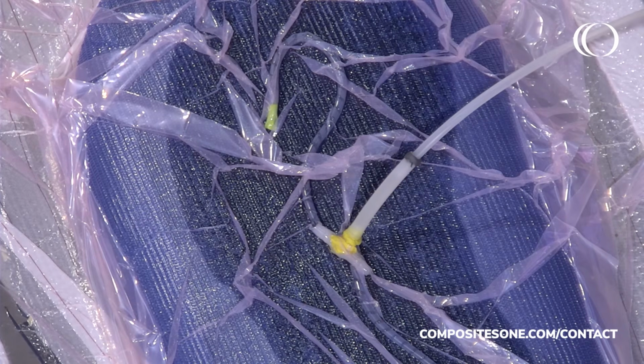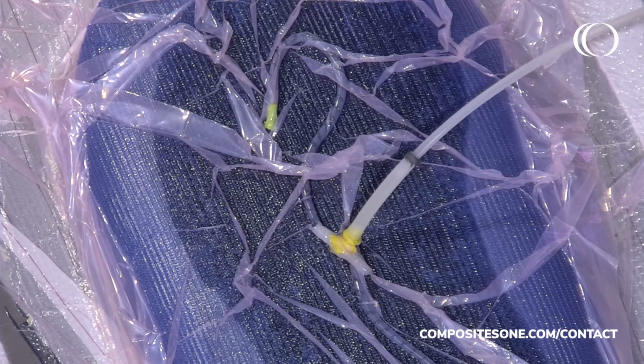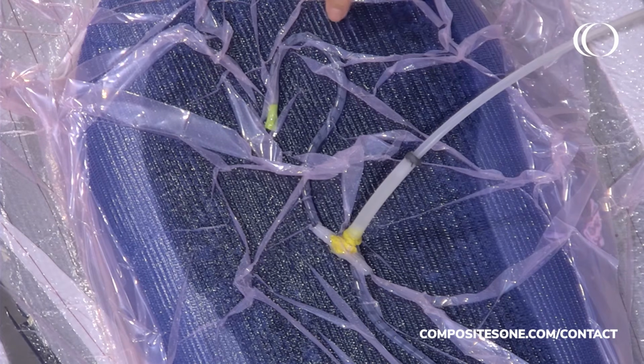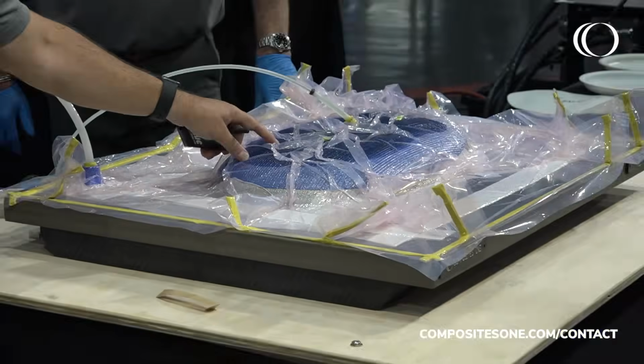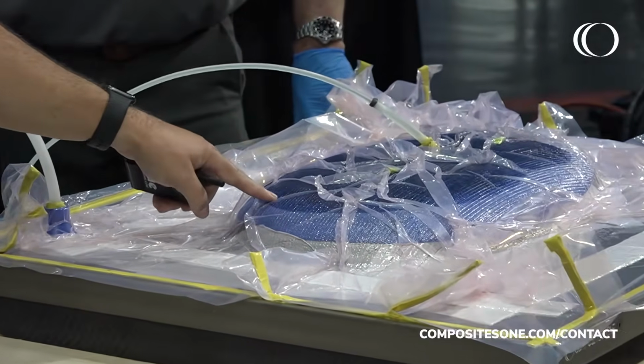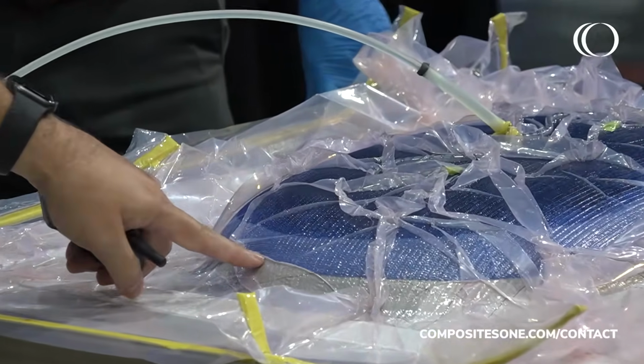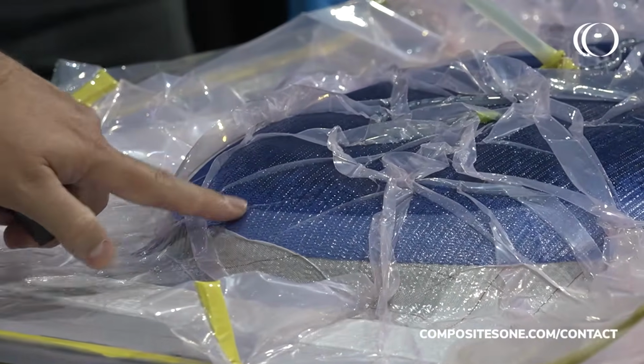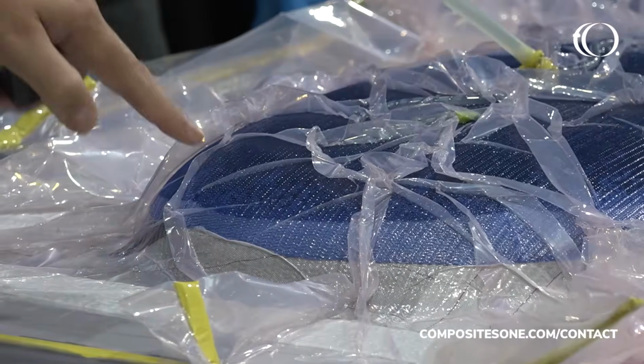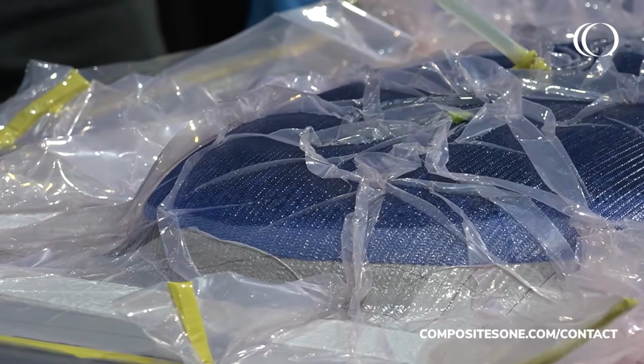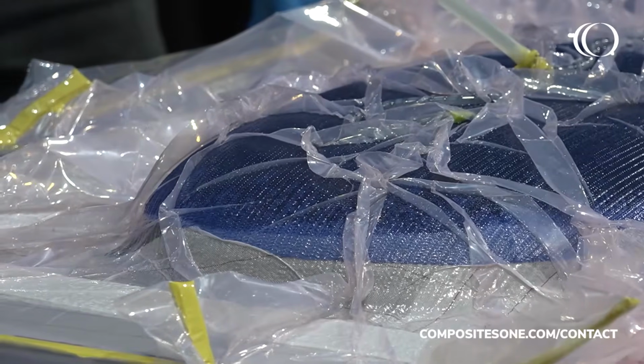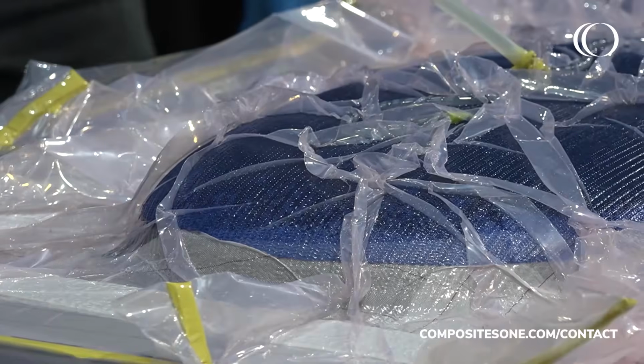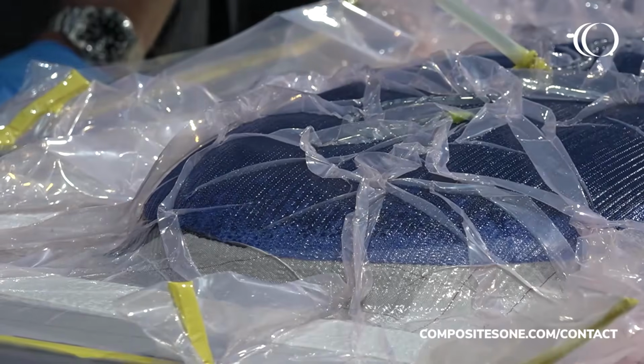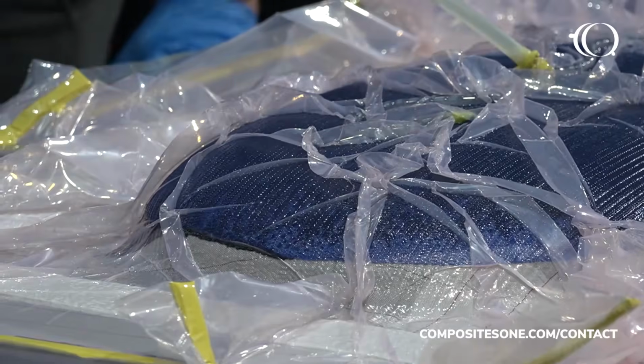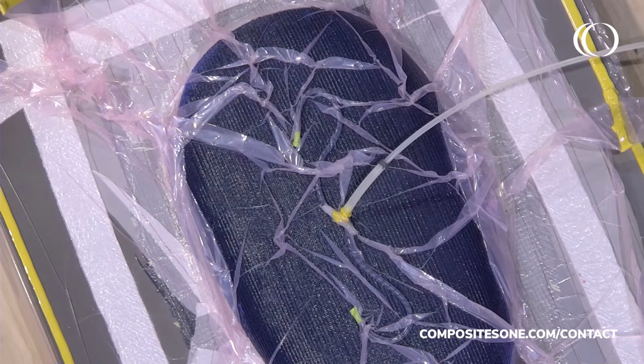So you can see the resin flowing through the InfuPly, and it's permeating down through the perforated release film. And on the mold surface, we're probably a couple of inches behind where the resin is saturating the preform. So once we get to the edge of the InfuPly, the resin will slow down significantly, and it'll start to saturate the preform through the thickness. You can see the resin flows very fast. The resin's probably about 75 degrees in our cup, but once it hits the mold surface, it's going to quickly climb up to the mold surface temperature, which we're at 110 Fahrenheit right now.